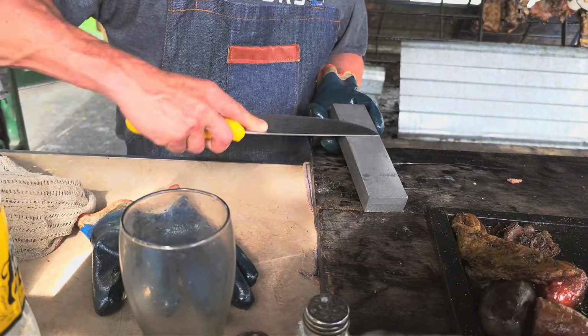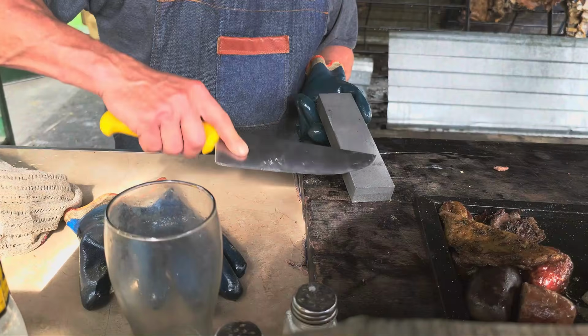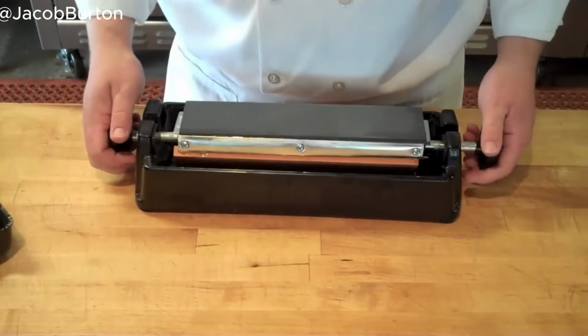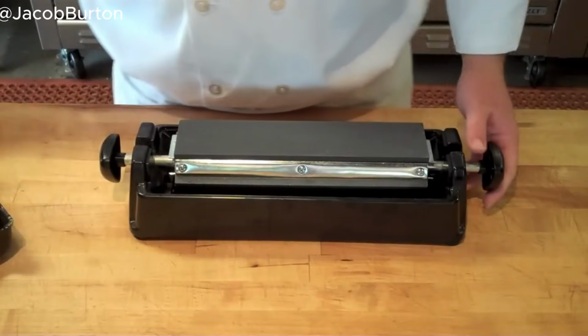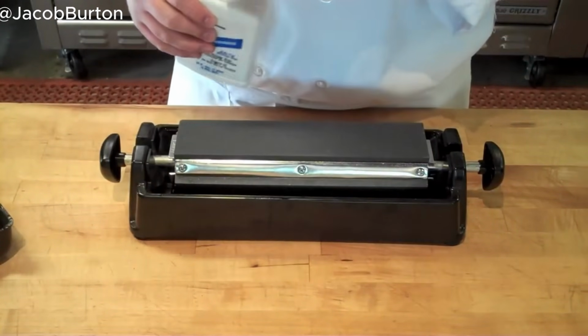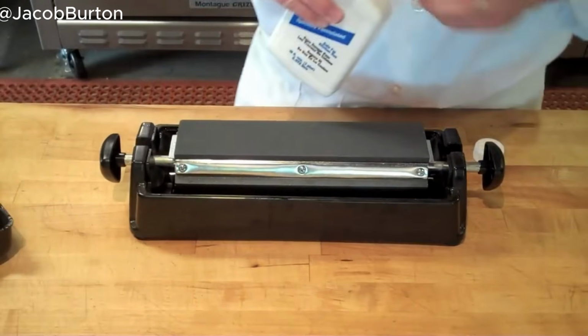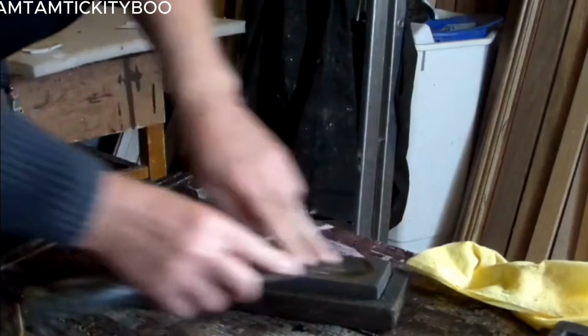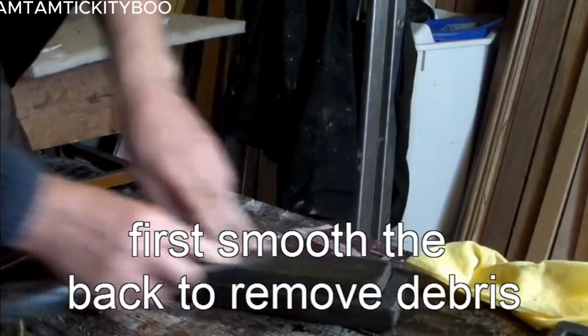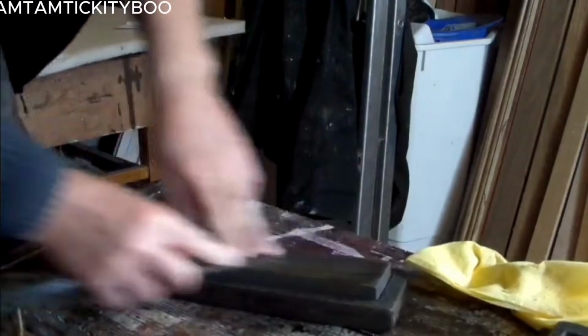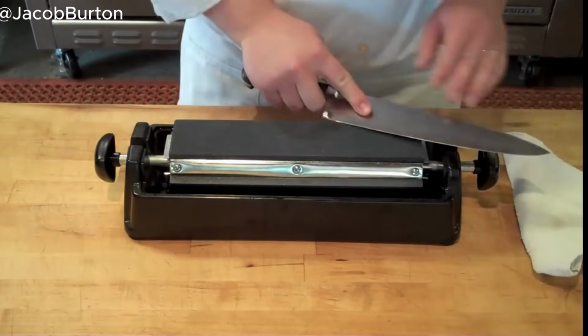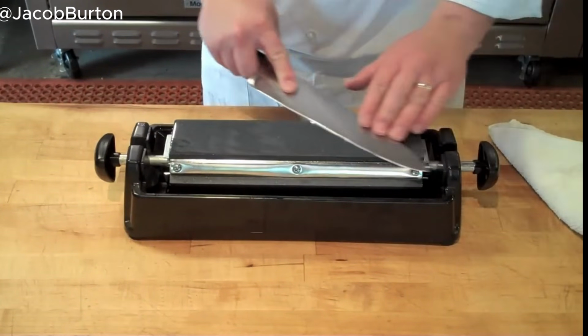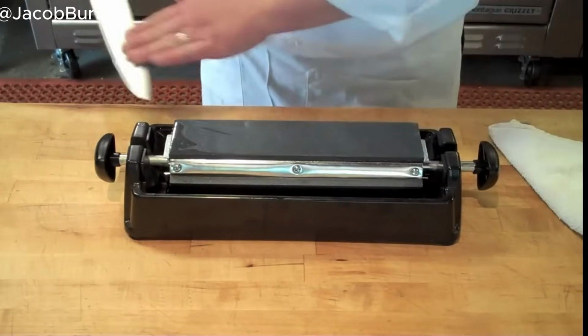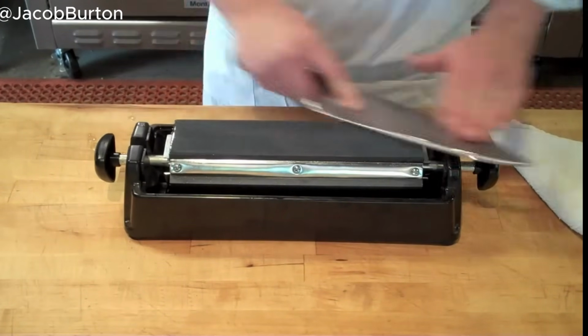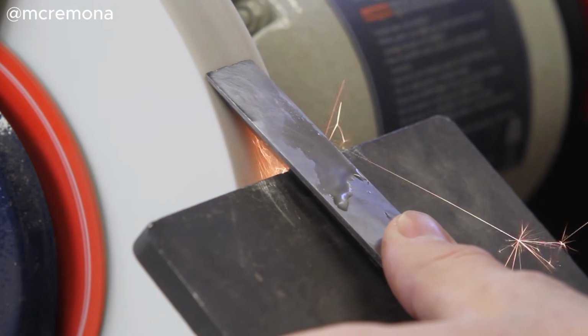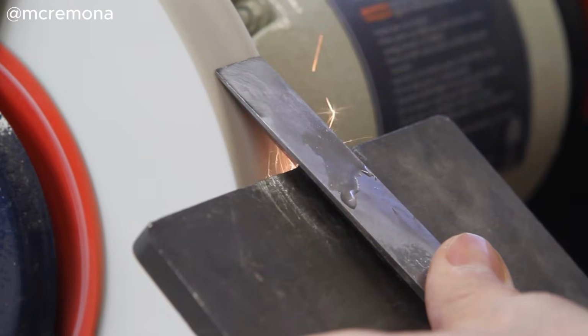The first mistake, and this is the one I see most often, is reaching for an oil stone. If you grew up sharpening Western chisels and plane irons, you probably have an India stone or an Arkansas stone sitting on your bench. Those stones work fine for Western tool steel. But Japanese high-carbon steel and oil stones are a bad combination. Oil stones cut too aggressively for that thin, hard steel layer. They leave deep scratches that become stress points, and those stress points are exactly where microchipping starts. That's what was happening to my chisels. I was creating the fractures myself every time I sharpened.